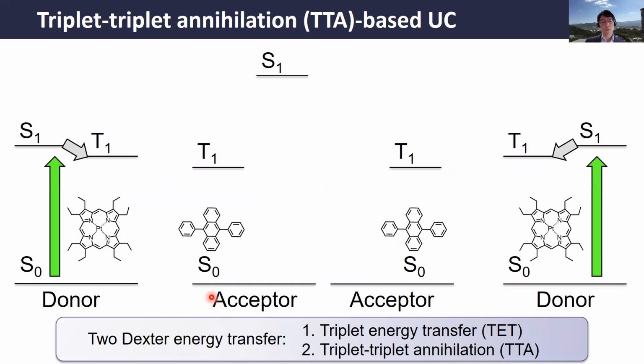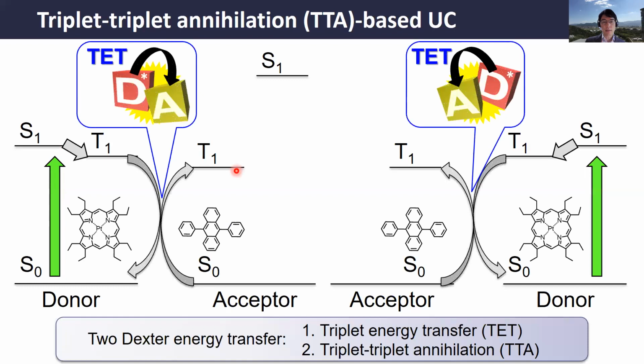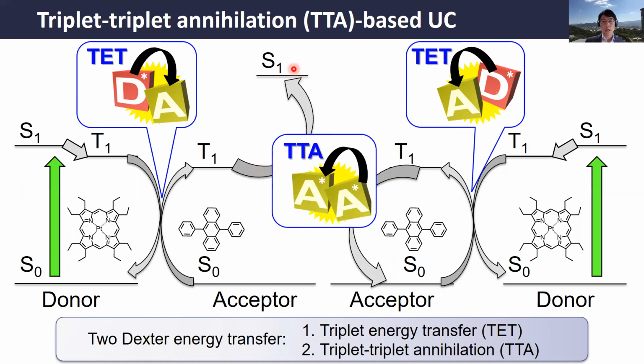Taking these two, donor and acceptor, let me briefly explain the mechanism of this TTA-based upconversion, also called sensitized triplet fusion upconversion. First, the donor PtOEP absorbs the light and undergoes intersystem crossing to become a triplet state, and this triplet energy is transferred to the acceptor triplet by the triplet energy transfer process. This is a Dexter energy transfer process. And these sensitized acceptor triplets meet again to undergo TTA, forming one higher energy singlet state, while the other goes back to the ground state. Eventually you get upconverted emission from this S1.